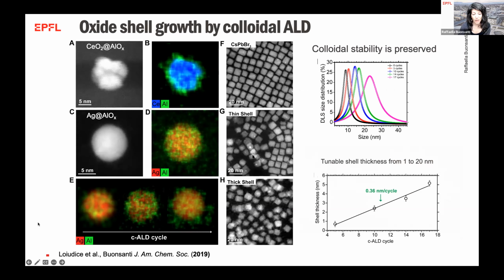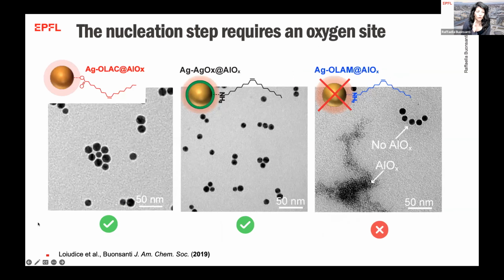Oxide, some perovskite, and that by changing the number of cycles, we could change the radius, the thickness, and that the shell thickness changes depending on the number of cycles. Now, we also started to learn a bit more about how this TMA reacts on the surface.